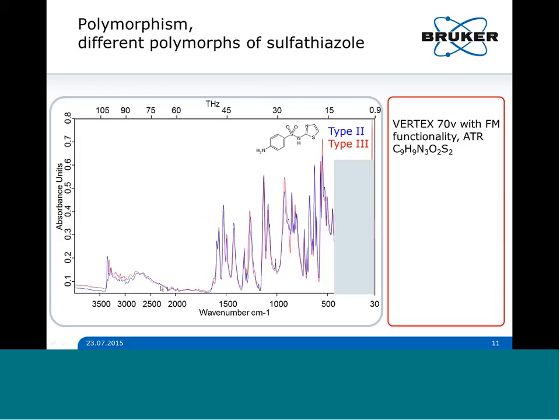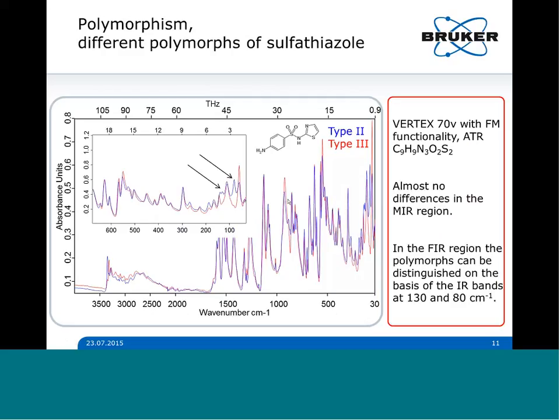The last example is the best one, because here we have a real polymorph. Example are these 2 crystal types of sulfathiazole, and if you look at the mid-infrared region, you can see really no difference. So you see these 2 spectra just cover each other very well. Maybe only somewhere some relative band intensity difference, but this is really difficult to calculate. And now we see the real additional value of the VERTEX FM functionality, because the only difference visible is in the FIR region, around 100 wave number, exactly at 130 this band, and 80 wave number.